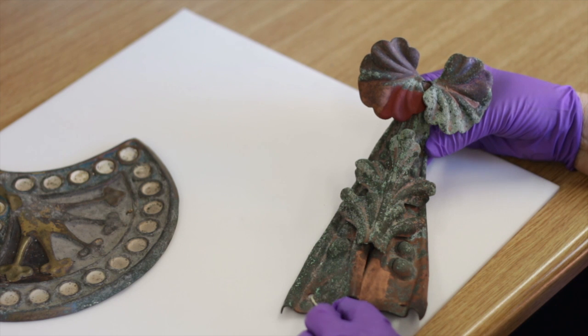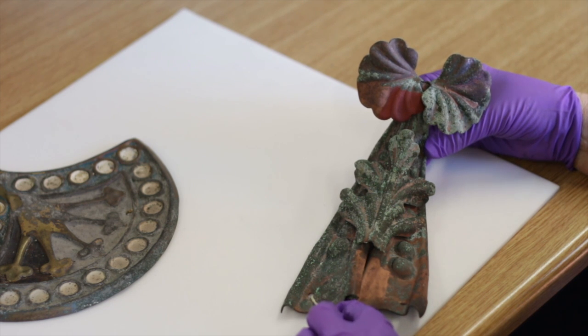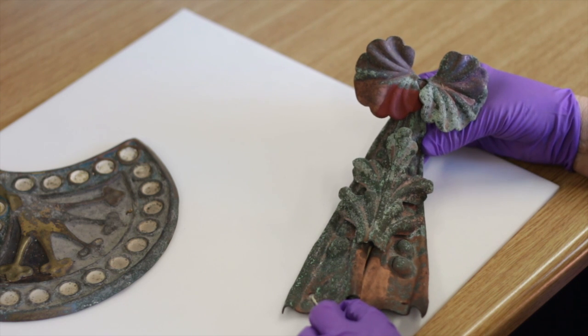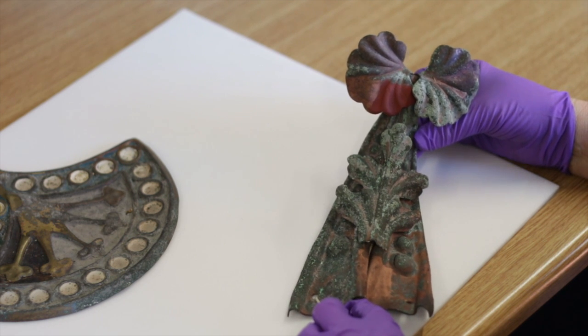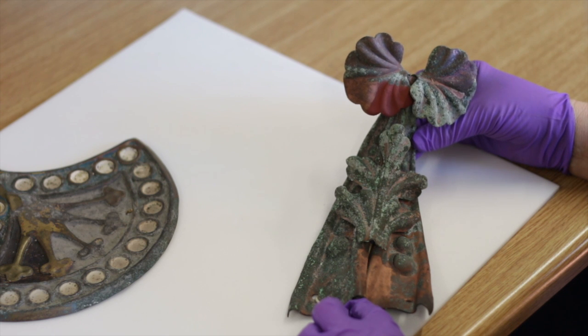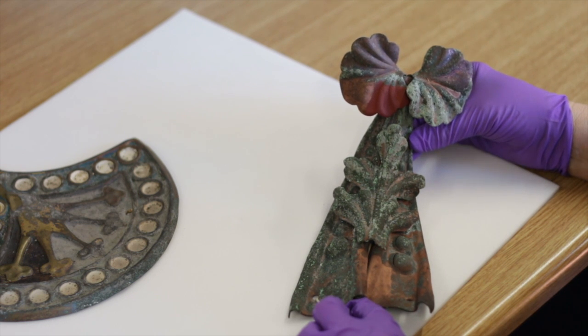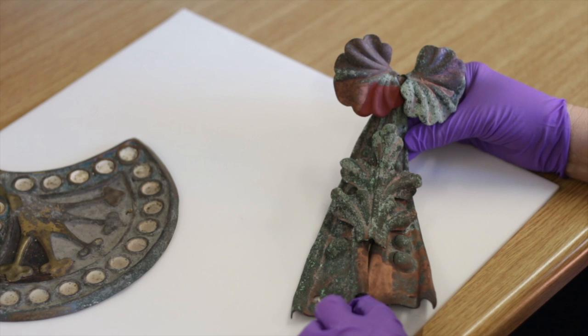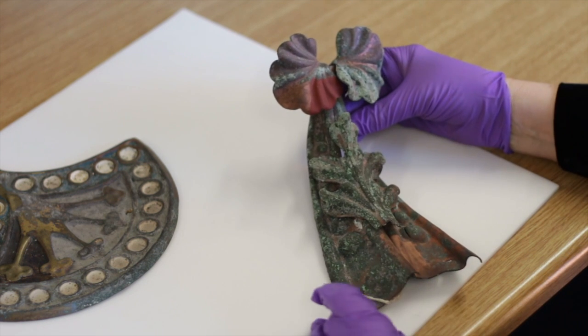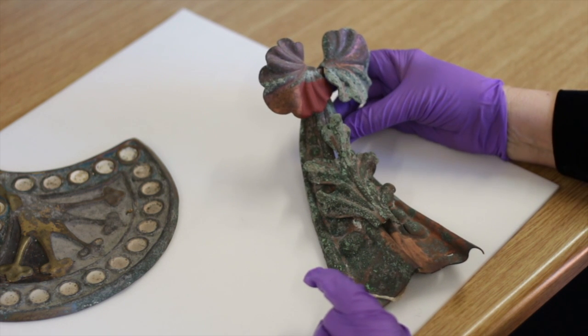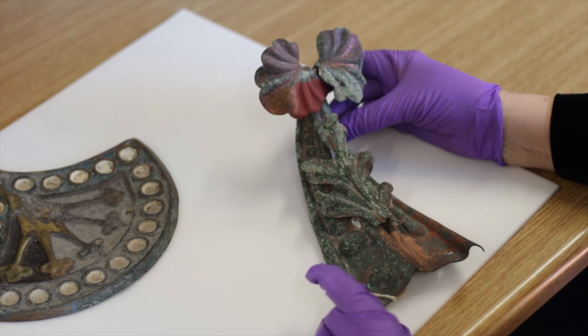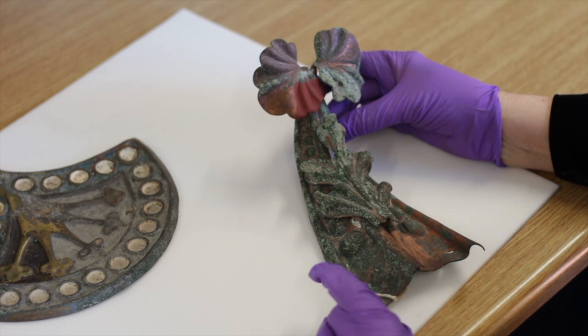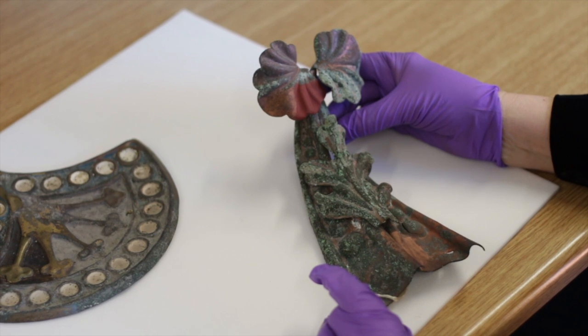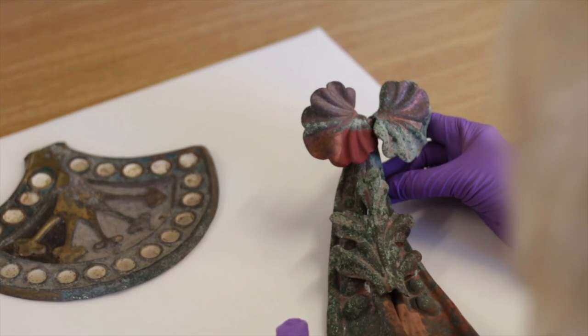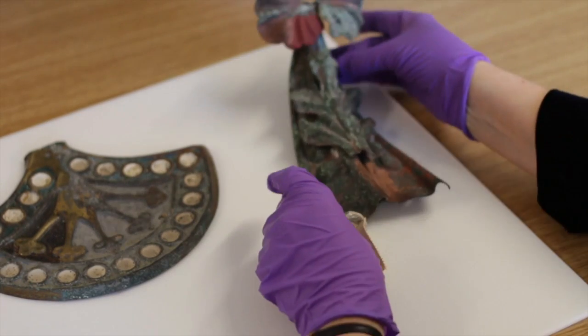Other methods were trialled using solvent gels containing chelating agents, and the chelating agents enable the corrosion to be made soluble. These were not so effective at the time, and that was why the decision was made to go forward with the air abrasive technique. The solvents and the solvent gels were less effective, and that's why it was decided to go ahead and recommend the use of micro air abrasives to effectively remove corrosion from the copper and the brass and the iron of the screen.